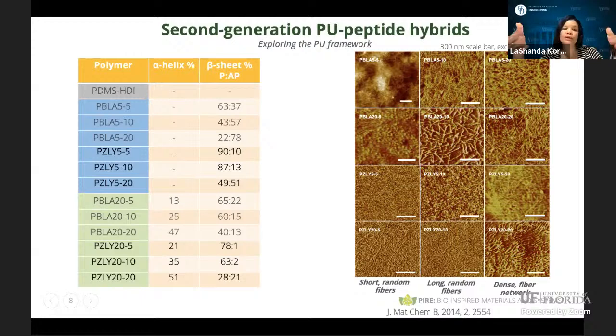And you can see that as you increase your block length, you are capturing more of the more stable beta sheet structure. For the 20 series, PBLA and polylysine, you see that as you increase the amount of peptide that's included in the system, you actually are increasing the helical content in the material system, while also varying, of course, the beta sheet parallel to anti-parallel structure. So we were able to achieve the secondary structure control that we wanted in this second generation of materials. We also wanted to look at the architecture of these systems, the morphology of them.